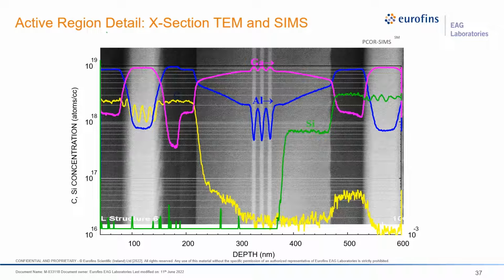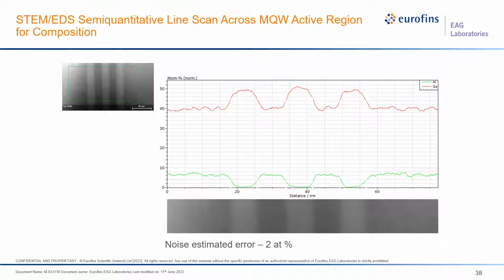However, the SIMS profile for aluminum does not resolve the MQW region as well as the TEM appears to. Fortunately, we have many techniques to bring to bear on a problem, so we can use TEM to better resolve the true aluminum content in these thin multi-quantum well laser areas. This slide shows a scanning transmission electron microscope image across the bottom of a multi-quantum well region, along with an energy dispersive X-ray spectrometry line scan across that same area. Here, the aluminum levels are fully resolved in the EDS line scan into layers of discrete composition, which is not possible with SIMS due to the energetic ion bombardment needed to generate secondary ions.